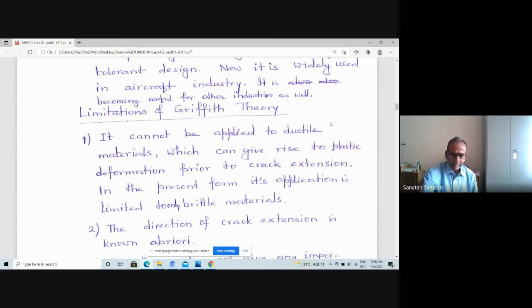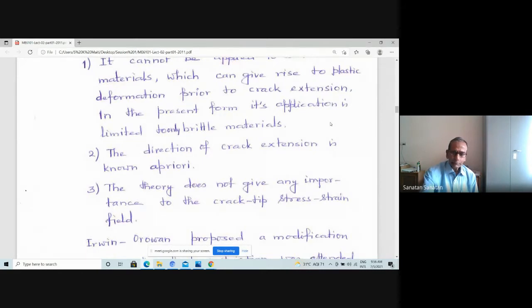This is one shortcut. And then, he considered the crack to be in the orientation perpendicular to the loading direction. So this is called the opening mode of crack extension. It cannot be applied if the crack is at an angle to the loading direction. And the other thing, classical understanding of failure of material is based on stress strain distribution in the whole body, and in the presence of a crack, this energy balance theory does not give any importance to the stress strain distribution at the tip of the crack, where classical people would like to take it up that there must be some typicality in the distribution of stress and strain near the crack tip, but it does not give any importance to it.